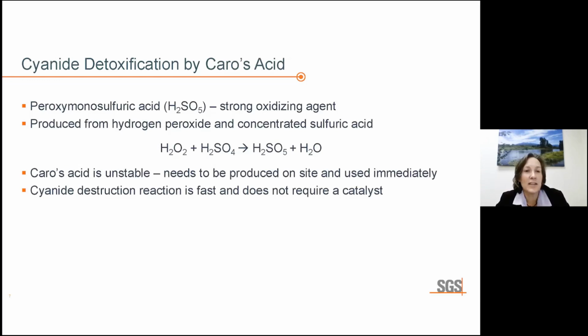Caro's acid, the peroxymonosulfuric acid reagent, is a very strong oxidizing agent. It is produced from hydrogen peroxide and concentrated sulfuric acid, and is not a stable acid, so it needs to be produced on site and used right away. Cyanide destruction using this reagent is really fast and doesn't require any catalyst.